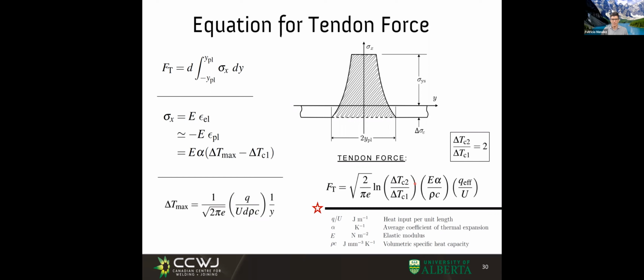So up to this point, we have just a number, if we say this is 2. Now here E is the Young's modulus, alpha in this case is the linear coefficient of thermal expansion, which is tabulated. Rho is the density of the material. C is the thermal capacity of the material, the specific heat. And this is Q in watts, effective, because all that matters is what comes in, divided by the travel speed. This term here is the actual heat input in joules per meter, or kilojoules per centimeter.